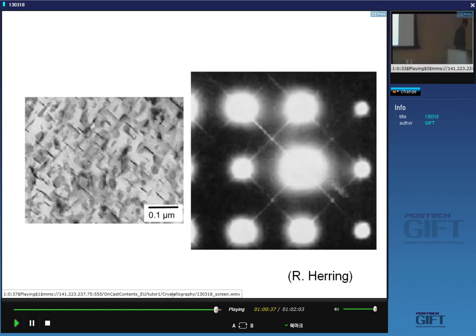And this kind of an effect that you see in diffraction patterns, which is streaking, is because these precipitates are thin. Okay, so if you have thin precipitates, then again, effectively, you get diffraction over a large value of theta, right? So these are incredibly thin precipitates, and therefore, instead of getting a spot,